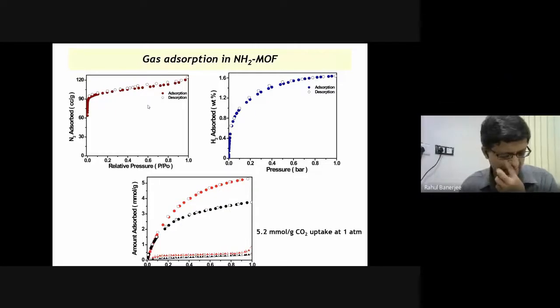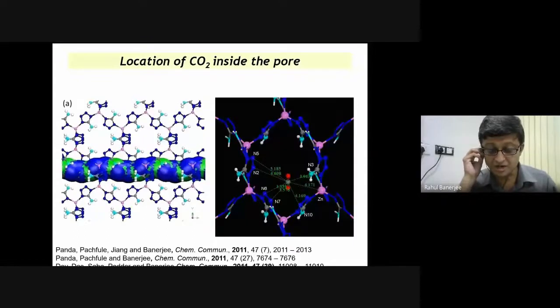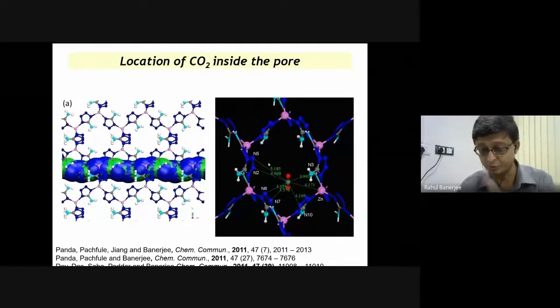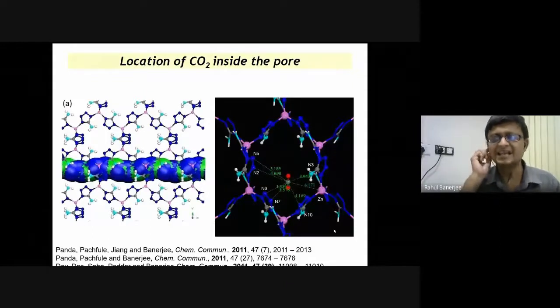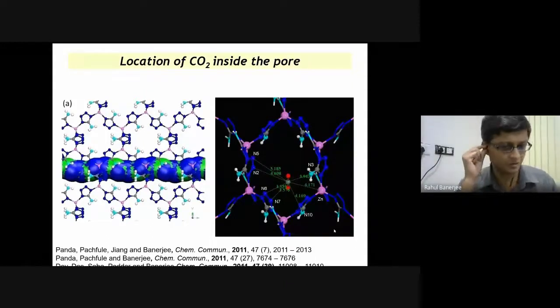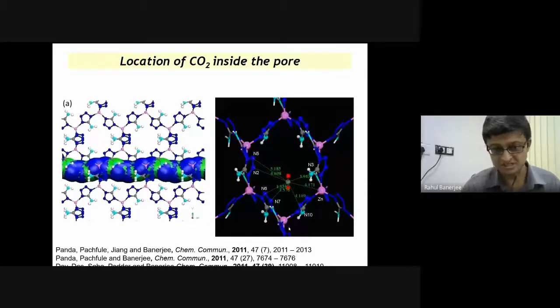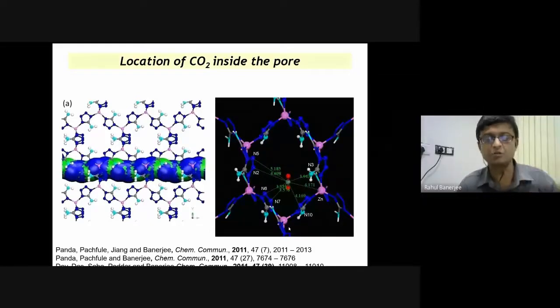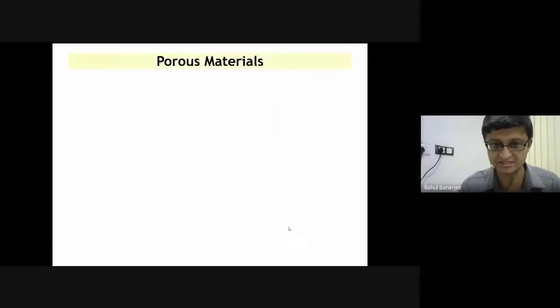We were not very happy about it, because these data mean nothing. We just checked the crystal structure, and we found out that the single crystal structure of this MOF contains a carbon dioxide inside. Well, this is only one pore. There are millions of pores and then millions of carbon dioxide molecules. Still, I don't think it is a really remarkable result, if you ask me, because it has to be 10 carbon dioxide per pore, or maybe 20. Then it will make some sense. So right now we are stuck at 1. But we are still working with them. It's a long-term process. So hope for the best, and let's see.